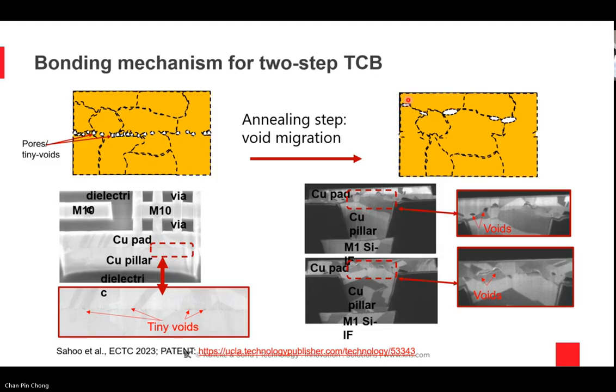We have to do a copper-dielectric bond, and then we have to follow it up with a TCB that is thermally induced, by expansion of the copper by heating it to high temperatures. So now, the beauty of this is that the way we do this is we let the pillar protrude slightly, and by slightly, it doesn't have to be a lot. Even a few thousand angstroms of protrusion are adequate. I mean, it's whatever you can actually achieve reliably on the surface, right?